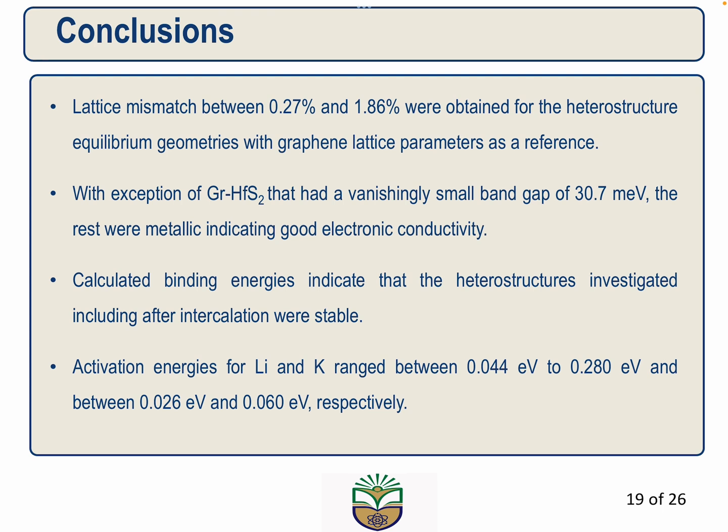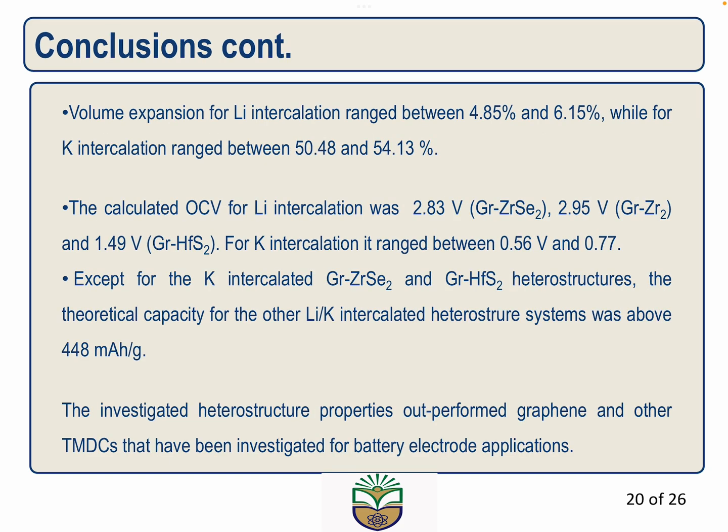We also considered the activation energies for the various systems, and we found that the activation energy for the lithium and potassium ranged between 0.044 electron volts to 0.28 electron volts, and between 0.026 electron volts and 0.060 electron volts respectively, an indication that fast kinetics for battery operations are possible using these heterostructures.